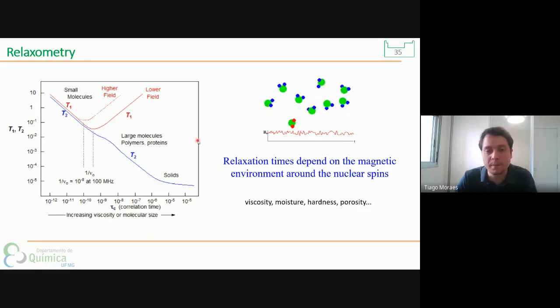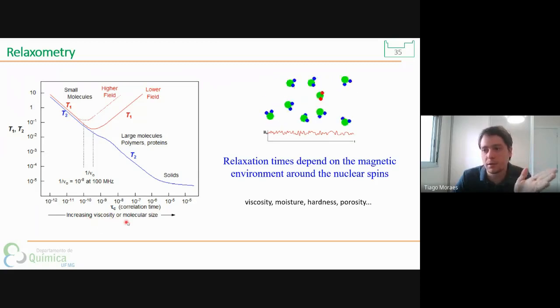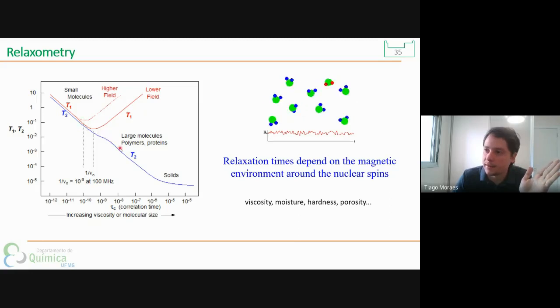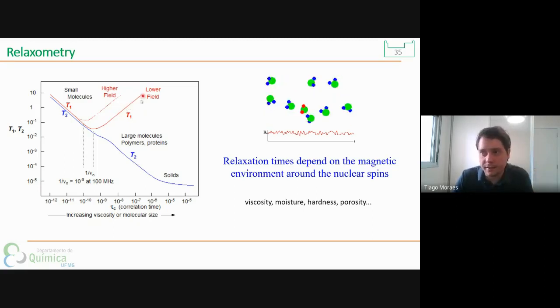And also, they depend on the mobility of the nuclear spin. So, as you can see here, we correlate the relaxation times, T1 and T2, with the correlation time of the molecule. You can see that T1 and T2 are associated with the mobility of the molecule. For liquid or small molecule samples, T1 and T2 are almost the same, but when you increase the viscosity or the molecular size, you see that T2 is shorter, no? And T1 is getting higher here, right?